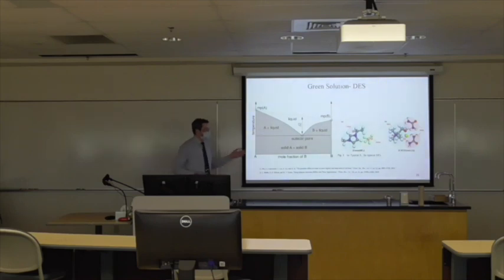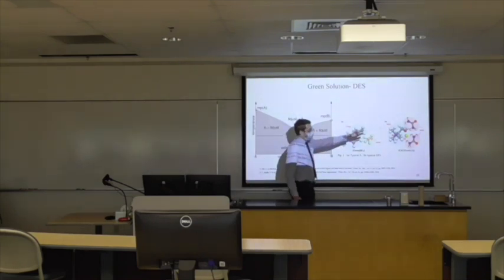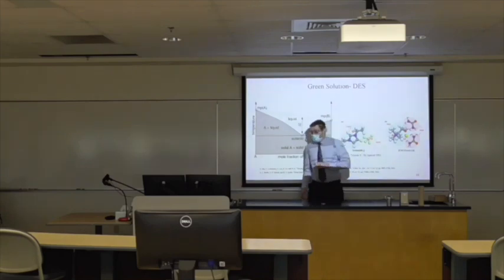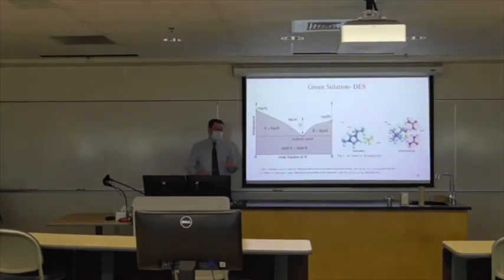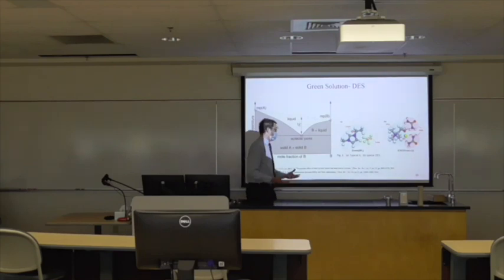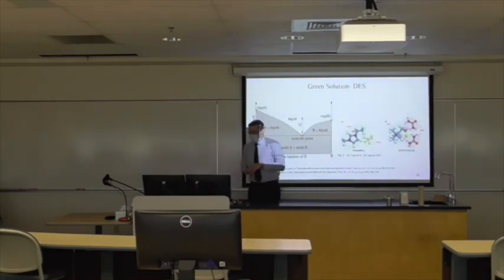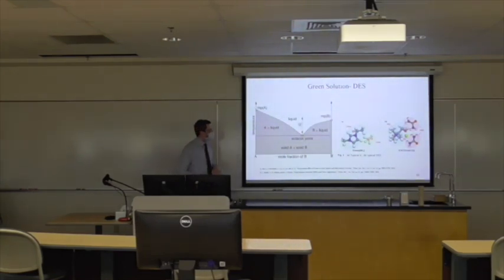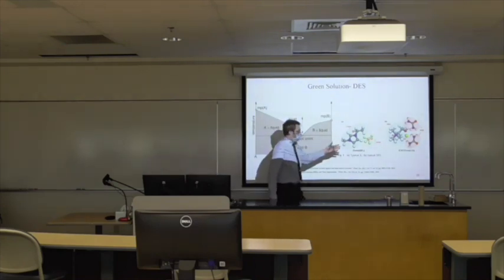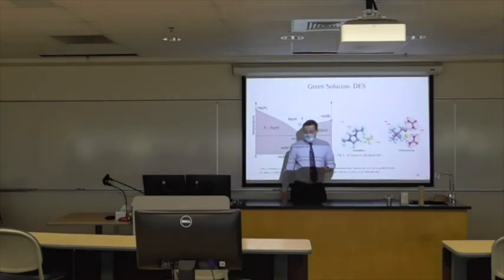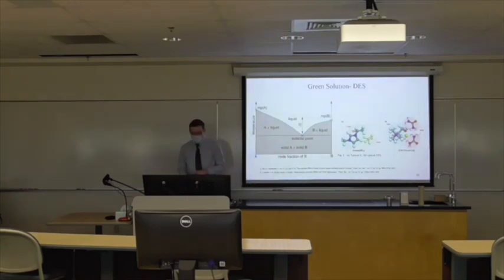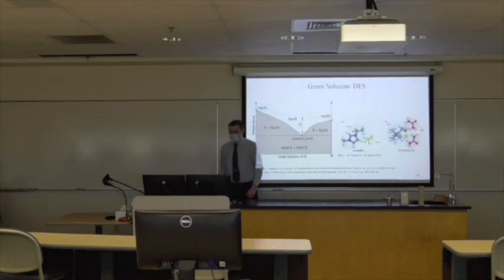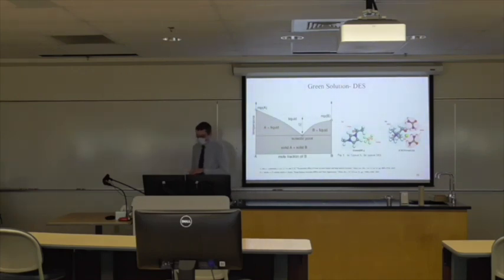For the eutectic solvents, we have a hydrogen bond acceptor and a hydrogen bond donor. And the hydrogen bond donor doesn't have to be an ion, the hydrogen bond acceptor doesn't have to be an ion, but often is. In this case, this diagram here shows choline chloride and urea used in a 1:2 ratio. And how it works is that the hydrogen bond donors are essentially pulling away the chlorine atom from the choline chloride, and that is going to effectively lower the melting point.